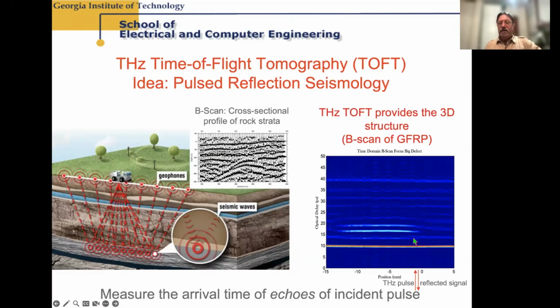So here is a cross-sectional rendering, or a B-scan, of a glass fiber reinforced polymer. This is a set of thin layers of polymer that also incorporate woven glass fiber fabric. We send in a terahertz pulse from below, and what we're looking at is the reflected terahertz signal as a function of position across this cross-section. So we can see the various layers in the structure, and here, both in the transverse direction and in depth, we see a delamination. This is an area we work in quite a bit in composites, looking for defects that have occurred either in manufacturing or due to impact. So again, this is just a clear example. We're going to go eventually to examples from advanced packaging.